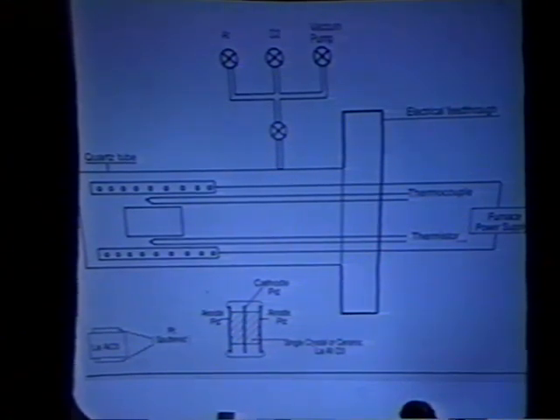And instead of using one sample, we put 2, so that mounting it is somehow easier. So we have a cathode in the middle, which is actually palladium foil, and 2 crystals around, squeezed by 2 other anodes. It's symmetric.